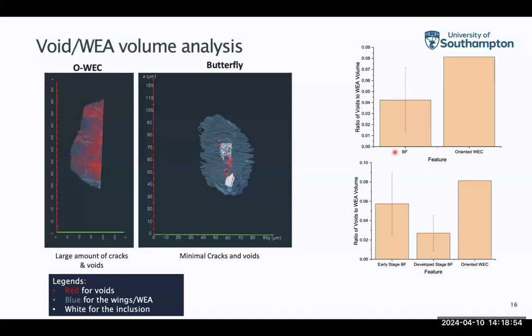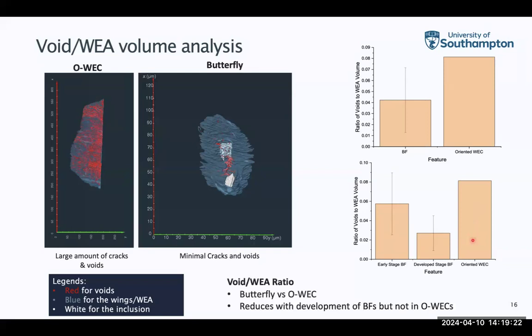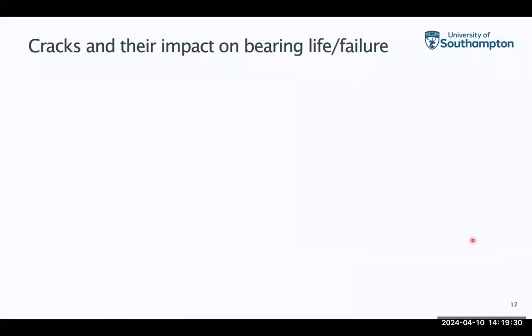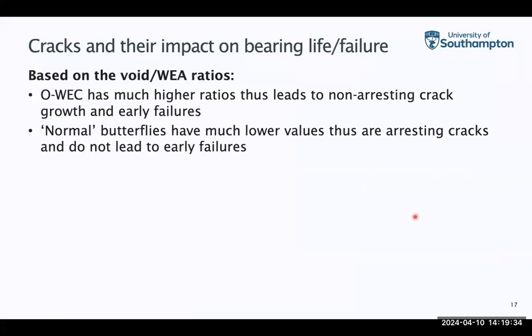We also compared the different stages of butterfly formation and found that as the butterfly development progresses, the ratio between the void and whitening area actually reduces. That's probably why butterflies don't lead to failure, because they have fewer cracks in development compared with the oriented white-etching cracks. That gives us some suggestions why some of these features lead to early damage and failures, and some don't. Based on these analyses, we conclude that the oriented white-etching cracks have much higher void to whitening area volume ratios. That's why they lead to non-arresting crack formation and growth, and then to early failures.